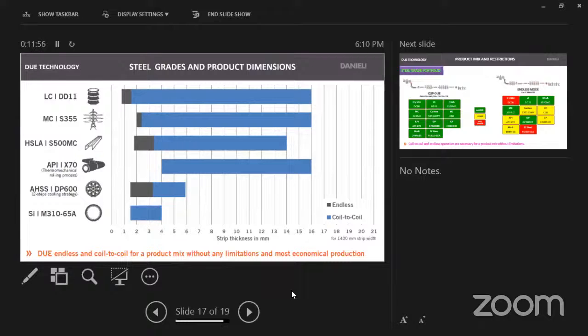For these grades, in endless also you can produce up to 6, 7, or 8 millimeter plate, because you can cut in the higher speed shear. But one major disadvantage is that you always have to switch on the induction heater. And there is a huge consumption of electricity, because there are 8 to 10 modules, and each is around 2 to 2.5 megawatt. So for the endless process, particularly in ESP, I have to switch on this induction heater every time, which is a huge cost for electricity.